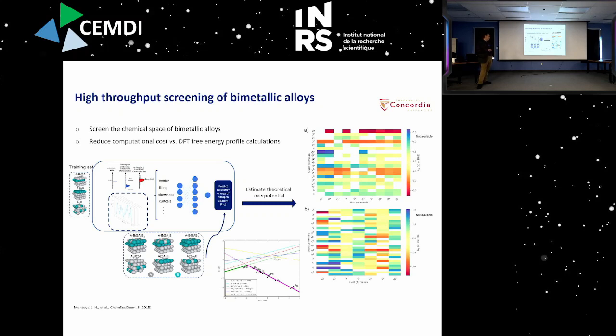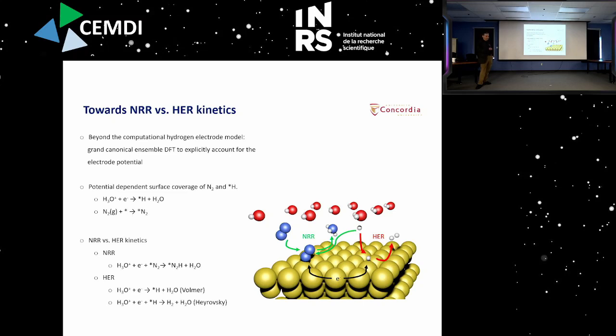or the nitrogen adatom onto these supports, because there is an empirically observed linear relationship between the adsorption of nitrogen and the theoretical overpotential. All right, so we make use of this, and then we get heat maps of the theoretically predicted overpotential for different types of alloys, and now we know that, depending on the type of structures, silver manganese or silver vanadium catalysts might be good potential catalysts. So we're now putting them to the test of DFT calculation of the free energy profiles and an experimental validation in Daniel's lab.